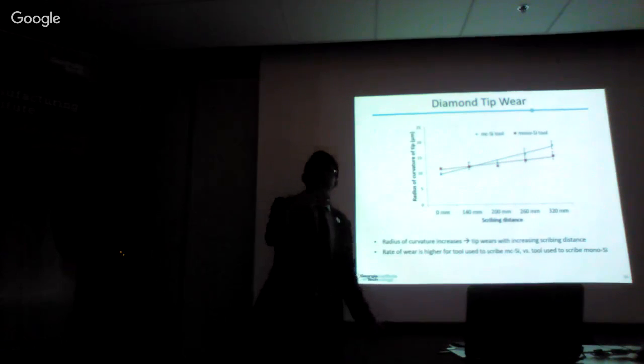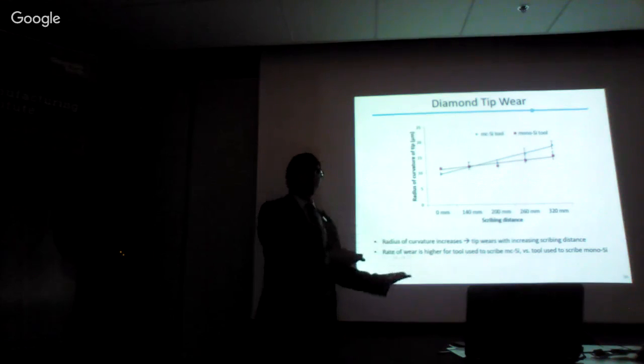Now both these diamond tips are having an increase in radius of curvature, which is expected because the diamond is wearing. However, if you compare the rate of increase of the radius of curvature, the rate of increase is higher or more aggressive for the tool scribing multi-crystalline silicon. You see it's a higher slope compared to the tool scribing monocrystalline silicon. So this is consistent with the story that the forces are higher in scribing multi-crystalline silicon using diamond indenters, and that is expected to cause higher stresses and more wear of the tool scribing multi-crystalline silicon compared to the tool scribing monocrystalline silicon.